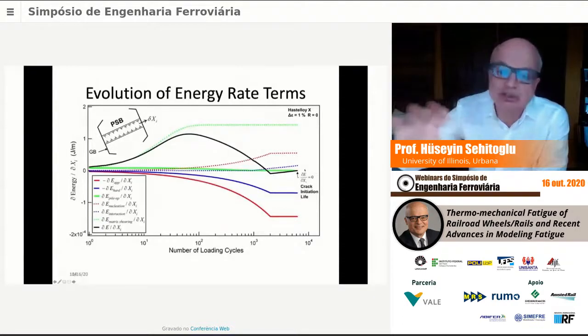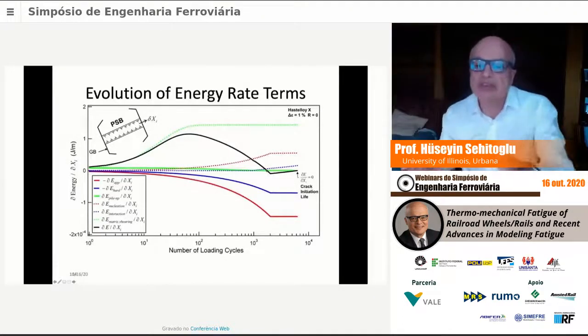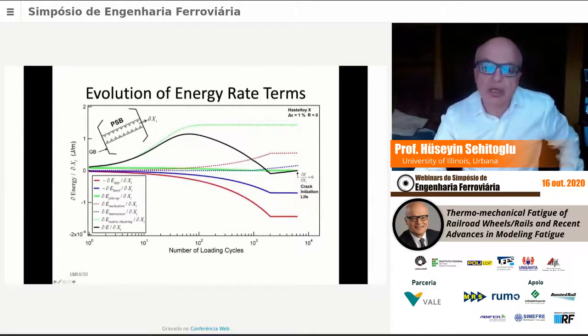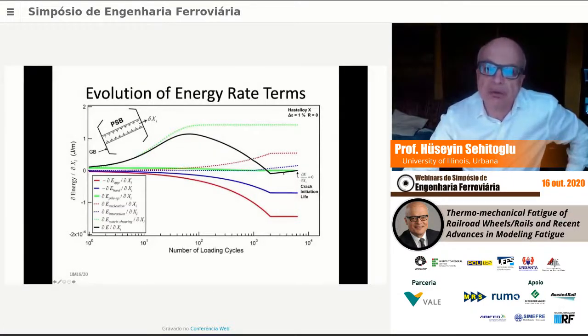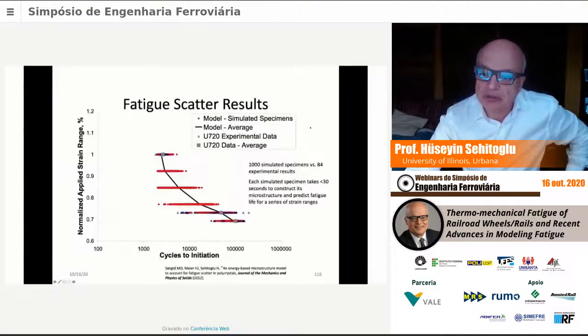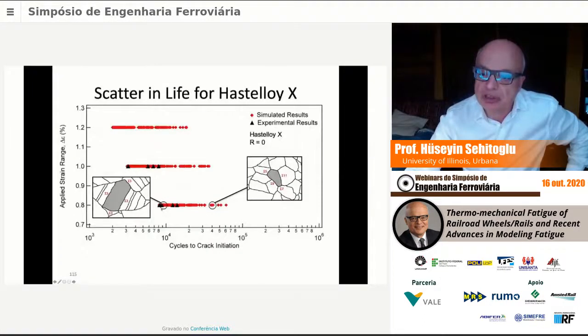And we can arrange the grains in different ways and get the evolution of the energy term. That's the energy versus cycles. That's the criteria for... It's not the first time it goes through zero. That's the unstable equilibrium. This is the stable equilibrium point here. That's the fatigue life prediction in our case. This is for Hastelloy X.